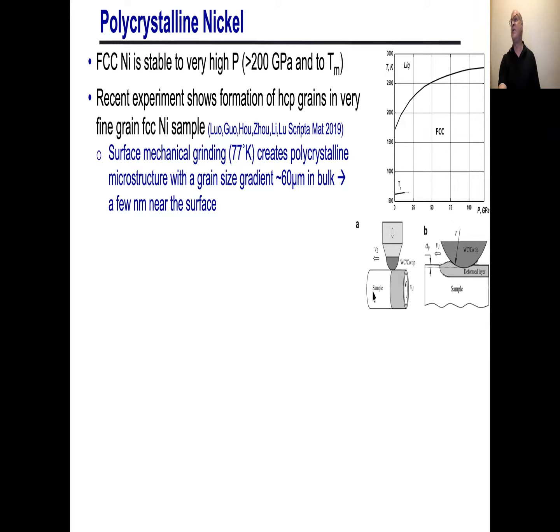So they take a sample, like a cylindrical sample, and they press down on it with a rounded tip like this. It's a tungsten carbide in cobalt tip. And they put a pressure on it, so pushing down onto the cylinder normal to its axis, and they rotate it. And they just go through the material and deform a layer near the surface. And what they end up with is, if you look in a radial direction around this cylindrical sample, a gradient in grain size that goes from about 60 microns in the bulk of the sample to just a few nanometers near the surface of the sample.